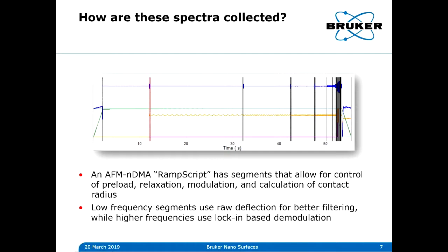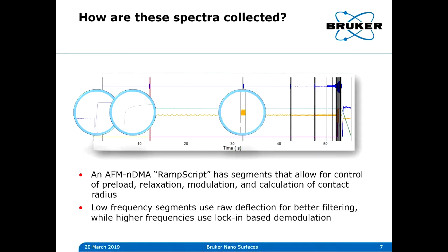And essentially, the ramp script with nano-DMA has segments that allow for control of the preload, so going into contact, and then a segment where we just hold the force constant for relaxation, and then a bunch of different modulation segments, and then finally a retract segment where we can calculate the contact radius. Depending on what the frequency of these modulation segments is, we may either acquire the raw deflection, which allows us to do better filtering and creep correction, or we might use a lock-in based demodulation if the frequency is high enough.